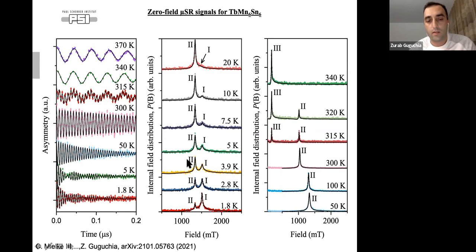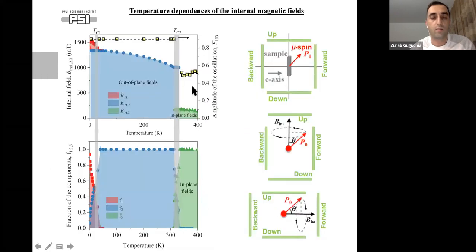So we again did detailed measurements of the field distribution inside the system, and what we see is that at high temperature we have a very low frequency component, and then a transition to a higher frequency component that continues down to 1.8 Kelvin, but then you have the appearance of extra components below about 20 Kelvin. And then again you have this competition between these two components. If I summarize here, this is the internal field as a function of temperature. We see this spin reorientation transition, which was actually reported previously from neutron diffraction.